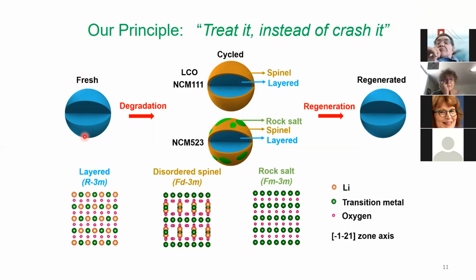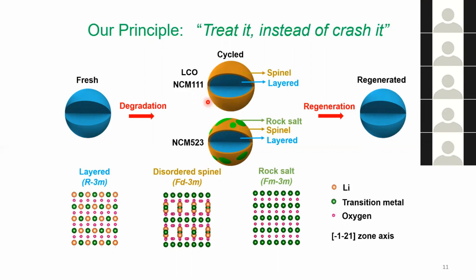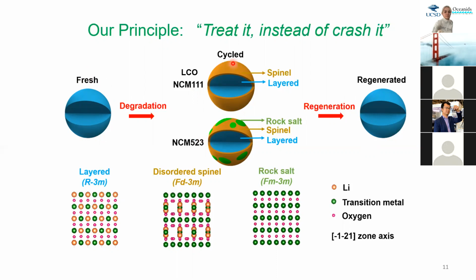If we use this blue color to mimic fresh materials, after a few hundred cycles, or 1 year or 2, you will have a process we call degradation, by inducing surface phase change to form new phases, which is something we do not want, highlighted here in orange and green. In the original phase, we have this blue color, which is a very good layered structure, with very ordered layers, 1 layer, 2 layer, 3 layer, and lithium stays inside. However, once we have the so-called spinel phase or rock salt phase, these phases do not follow this ideal layer structure.